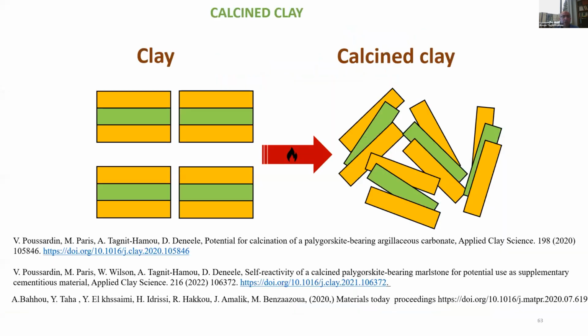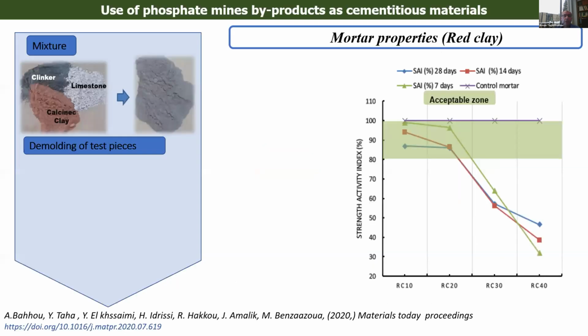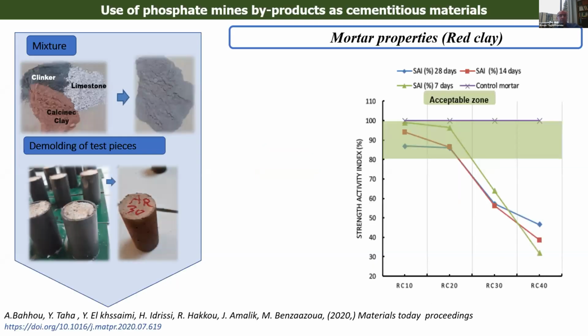When you study this, of course, this is just a presentation of calcined clay, and you can see these papers done by Victor Poussardin and also Bahou. When those materials are calcined, they show very good performances. You can see here, this is the clay, which is calcined, and you can see that the strength activity index is very good.